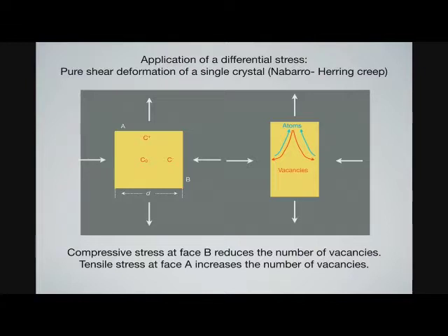Very briefly, that relates directly to the experiment you did last week with the dead weight apparatus. Essentially, in the air, in any kind of fluid, you have a hydrostatic state of stress, but with the dead weight apparatus, you created a non-hydrostatic state of stress, and because of that, you started to deform the material, the wax that you looked at. If you look at this macroscopically and try to come up with a model, a non-hydrostatic state of stress will affect your defect concentrations. That's really the key part here.